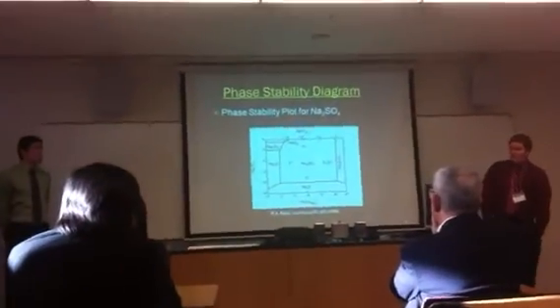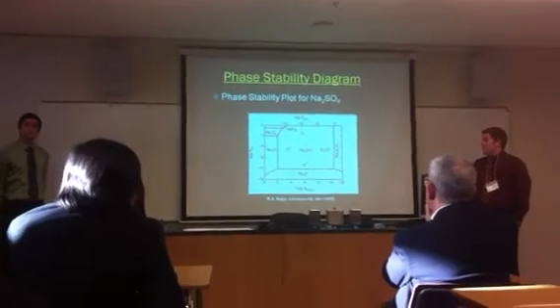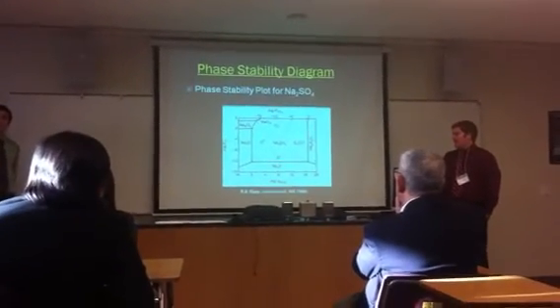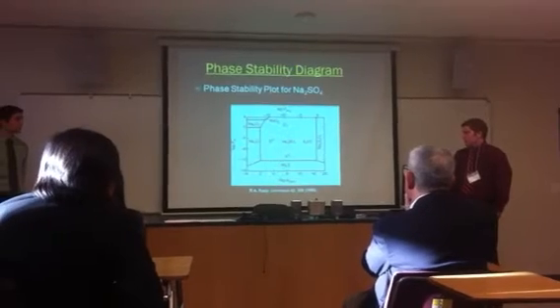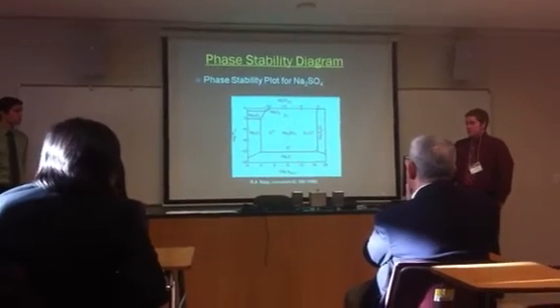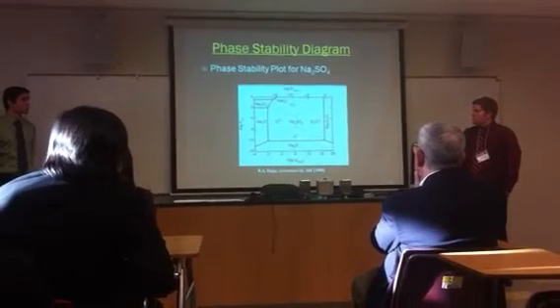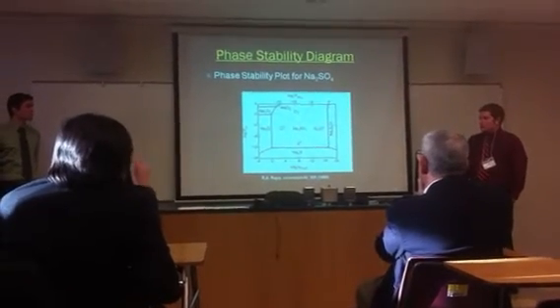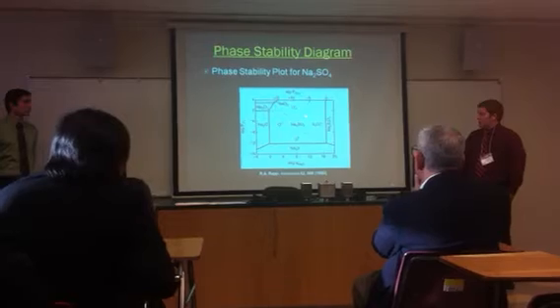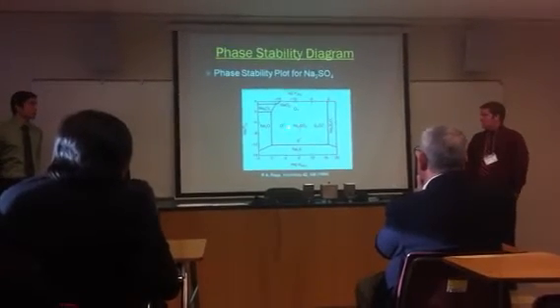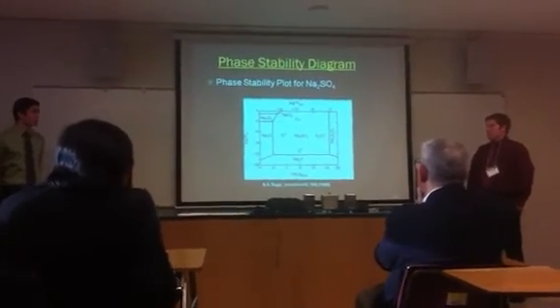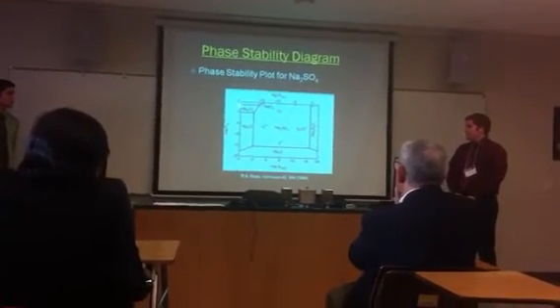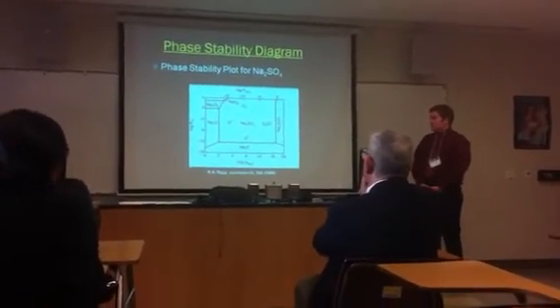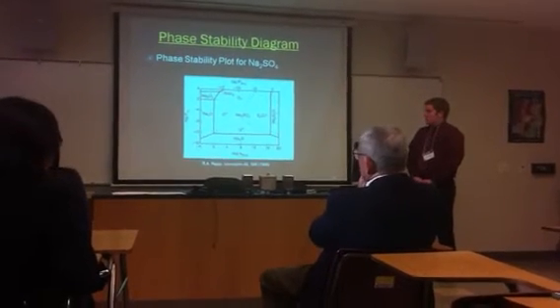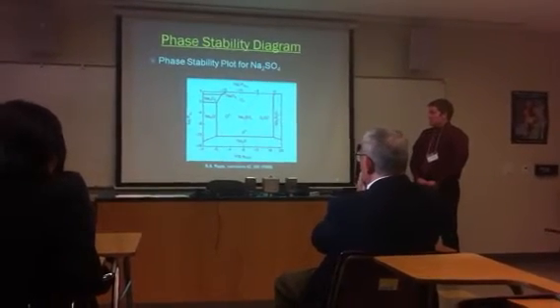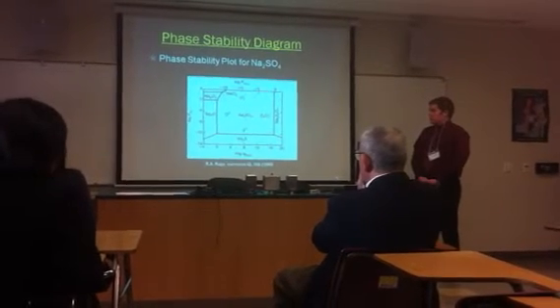Now here we have a phase stability plot for sodium sulfate. On the y-axis, we have the log of the partial pressure of oxygen. On the x-axis, we have the negative log of the activity of sodium oxide. And here at the top, we have the log of the partial pressure of sulfur trioxide gas. And here, right in the center, is where our conditions actually form the salt. But as we raise the partial pressure of oxygen, we're going to peroxide or oxidize the sodium samples more, and as we increase the amount of sulfur in our conditions, we're going to create these sulfur-rich compounds.